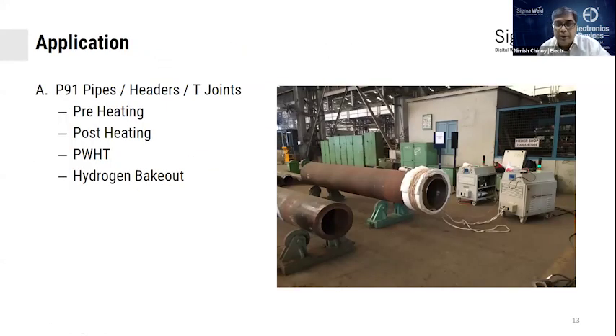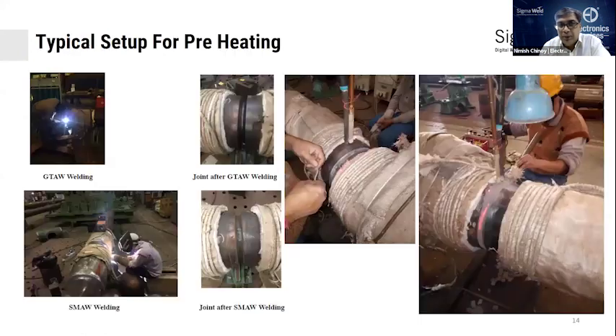Now, if you're doing heavy wall pressure vessels or boilers, here is a header made out of P91 material, which needs to be heated on the edges before it's welded. You need to also do post-heating, then PWHT and bakeout. These are the typical setups. You will first wind it up, preheat to 200 degrees. You can see the welder welding while the coil is in place.